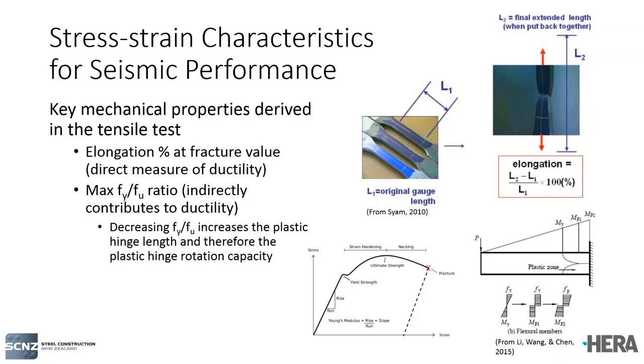You measure the new distance between the gauge points, L2, which includes plastic non-recoverable deformation, and the elongation percentage at failure is the new distance between the gauge lengths, L2 minus the original one, divided by the original length, and that gives us our elongation at fracture value.